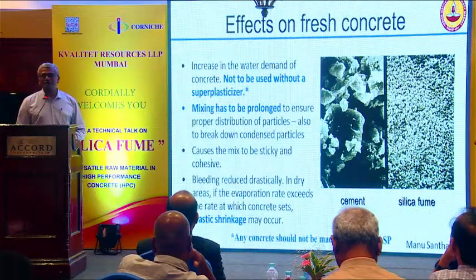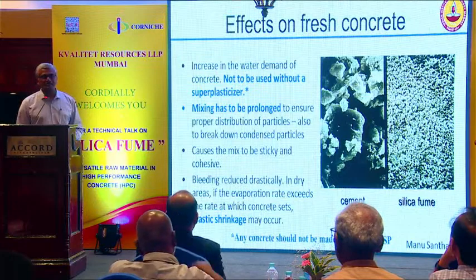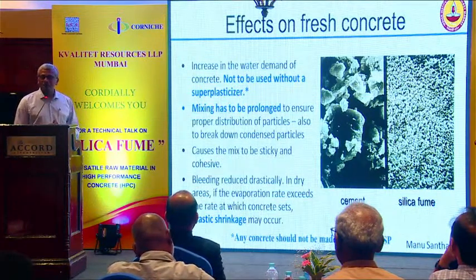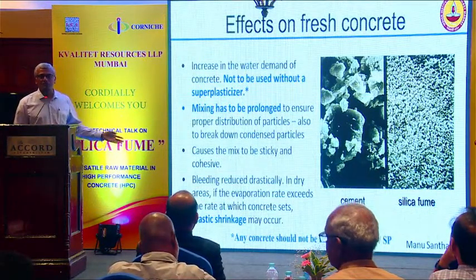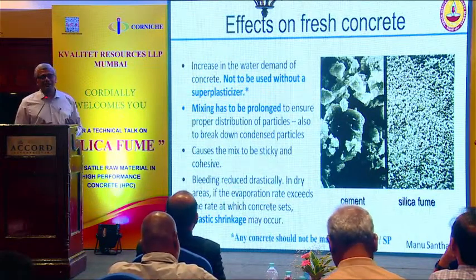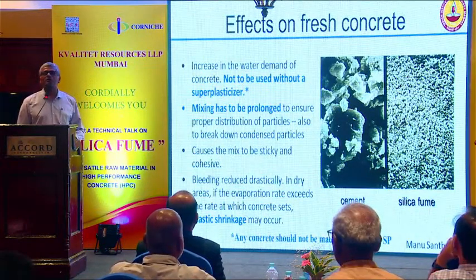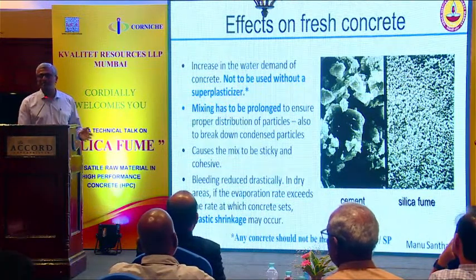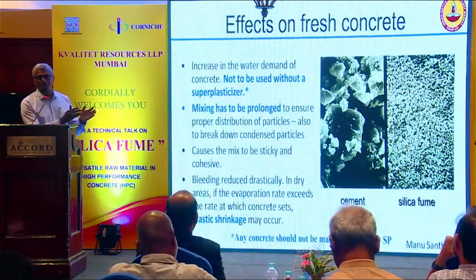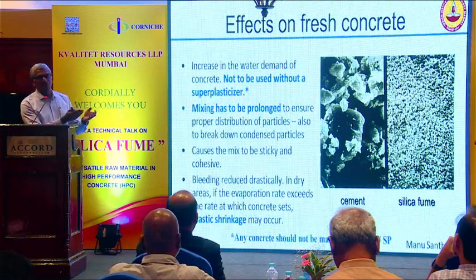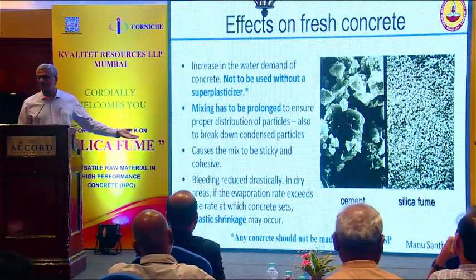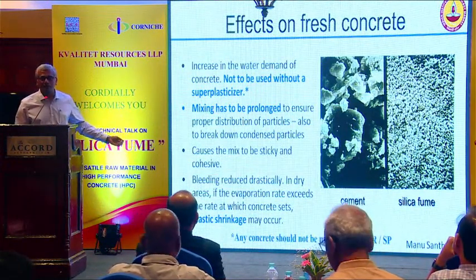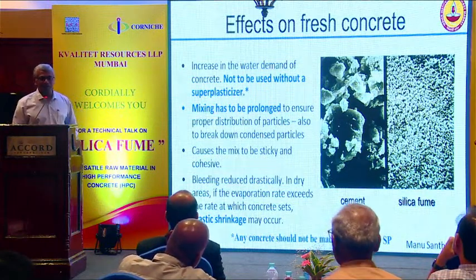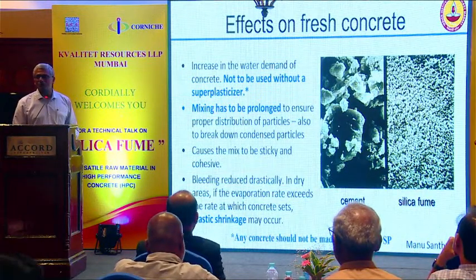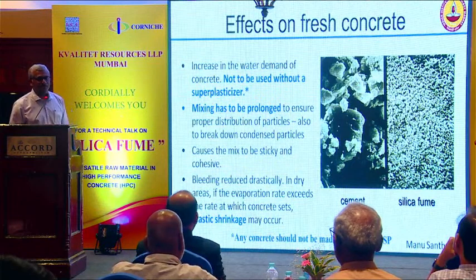You can optimize your mix, use less cement to produce the same grade of concrete if you use a super plasticizer. So any concrete today which does not use water reducer or super plasticizer is not sustainable in my opinion, because we're using too much cement to get the workability. Because water cement ratio is fixed, so you increase the cement to get the water to get the workability. But here with the super plasticizer you don't have to do that. So that is true of any concrete. You have to use water reducer or super plasticizer to see efficiency happening in concrete.